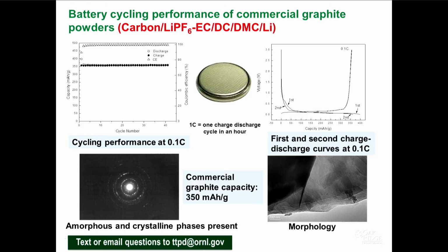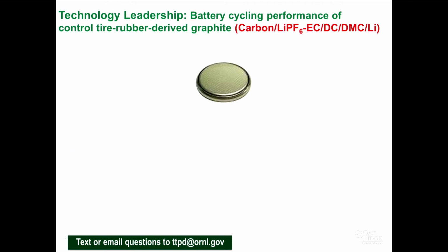And this is the morphology. So these are commercially available graphite, something we tested, and it gave like 350 milliamp hour per gram. And also if you do the rate performance, you couldn't go to very high rates. That means you can't do fast charging using some of these commercial graphite, and I'll show some data with the sulphonated batteries. So let's look at the controlled tire rubber derived graphite.